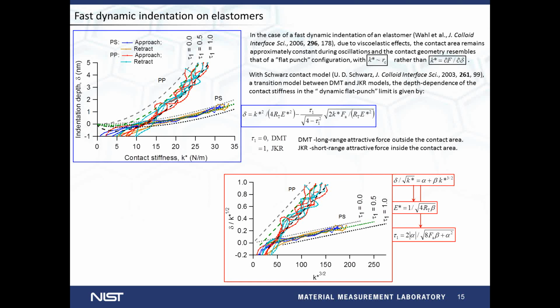For the contact mechanics analysis, we chose the Schwarz model, which is a transition contact model between the known DMT and JKR models. Unlike a DMT or JKR analysis that fixes the value of the transition parameter, either 0 or 1, with the Schwarz model, no a priori assumption was made for the value of the transition parameter, which instead was considered a free fit parameter.